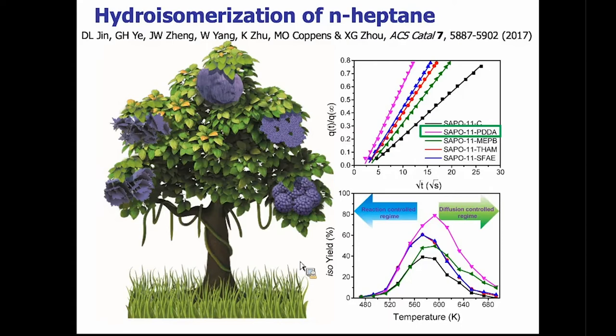Okay. And so we have looked at this catalyst that I showed you just before, and we have demonstrated the capture of this molecule and converting it efficiently and effectively into the desired iso-branched molecules without being broken down. So if the catalyst is not properly structured, the molecules would be broken down to small pieces, light molecules, it's called cracking, and make undesired molecules. And that is because molecules linger too much within the pores and they can't move out quickly enough. So the lingering leads to advanced reactions, which you don't want. And that's shown on the figure underneath there.